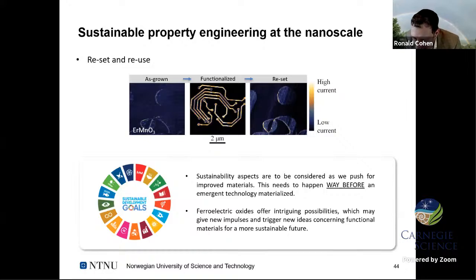So David Vanderbilt asks, regarding dislocations, is the functionality at the 1D partial dislocation, or is the functionality on the 2D stacking faults that span between the dislocations? That is a question we cannot answer at this point. When we are doing the conductance measurements, we are measuring an area with a lot of dislocations in there. So what we can measure is that we have a dislocation-rich area and they're only there and not outside, and where we have the dislocations, conductance is reduced. Based on the DFT calculations, we can now extrapolate that this is where you have the oxygen vacancies sitting, and they are affecting the conductance.